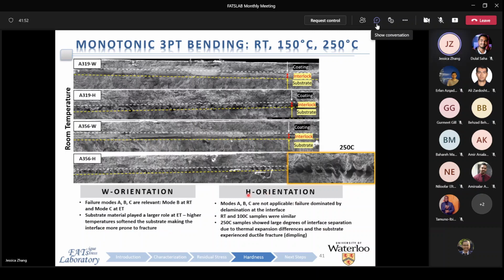The failure in the H orientation was modes A, B, and C is not applicable, but the failure was dominated by delamination at the interface. So while the room temperature and 100 degrees Celsius results were actually similar, the 250 degrees samples showed large degrees of separation. So I guess the difference in thermal expansion affects this particular orientation at higher temperatures a lot more.